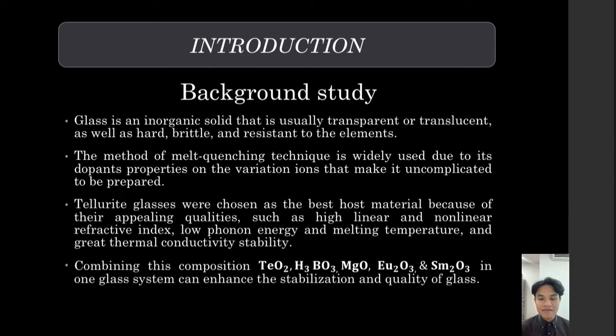Tellurite glasses were chosen as the best host material because of their appealing qualities such as high linear and non-linear refractive index, low phonon energy and melting temperature, and great thermal conductivity stability. And lastly, combining this composition of tellurium oxide, boric acid, magnesium oxide, europium oxide, and samarium oxide in one glass system can enhance the stabilization and the quality of the glass.